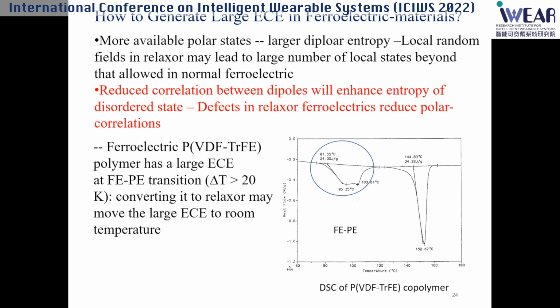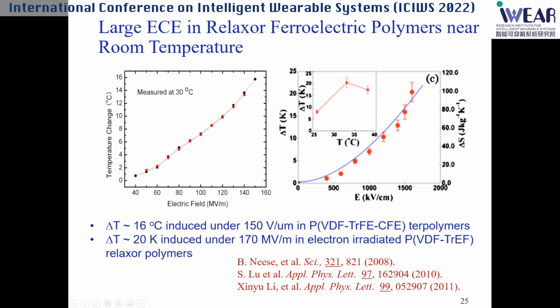Once we thought about this, it wasn't so hard to show — about 10 years ago we showed that in the relaxor, produced by high energy irradiation, we can get about 20 Kelvin temperature change. And also with polymer, you can get more than 16.